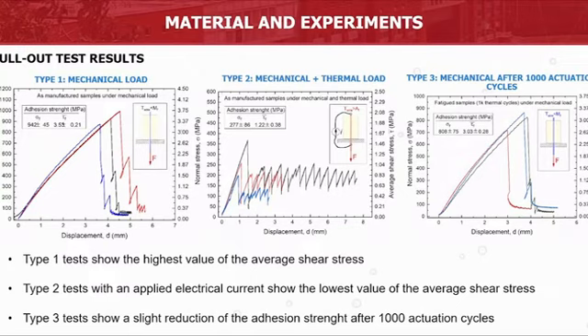And finally, type 3, compared with type 1, is showing only a slight reduction of the adhesion strength, also after 1,000 actuation cycles. So in the design of this composite material, the temperature plays a very important role in the adhesion strength.